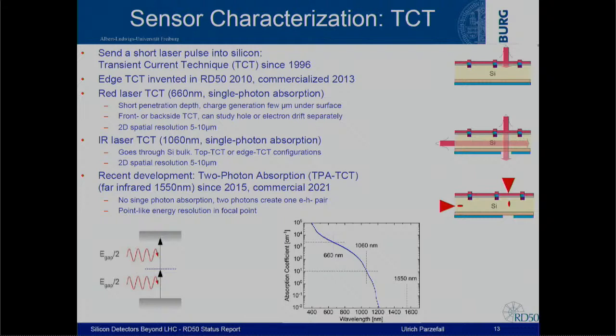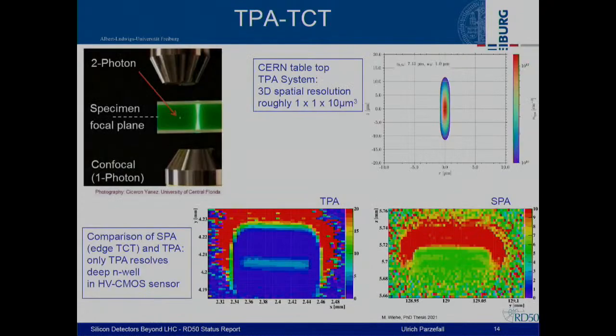The most recent development is to use a laser that, on this plot, has no absorption coefficient at all, because there you need two photons at the same time, within a femtosecond or so, to bridge the band gap. In this two-photon absorption process, you actually get a very point-like resolution that allows you to study effects deep into your sensor.